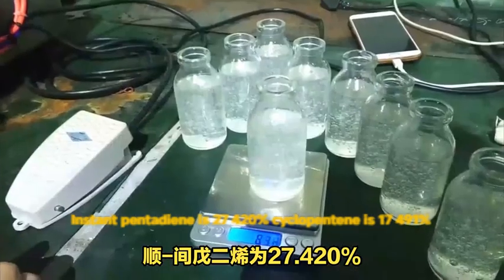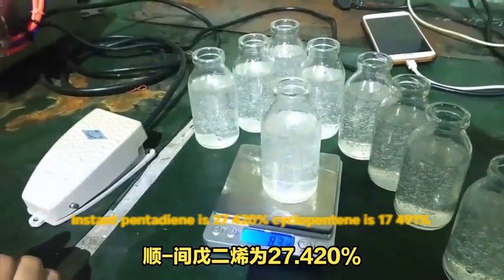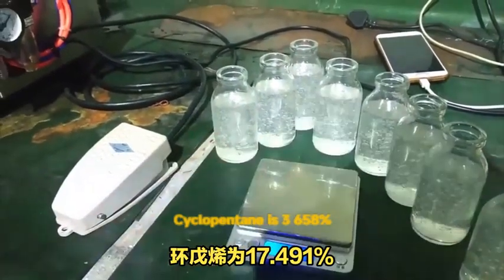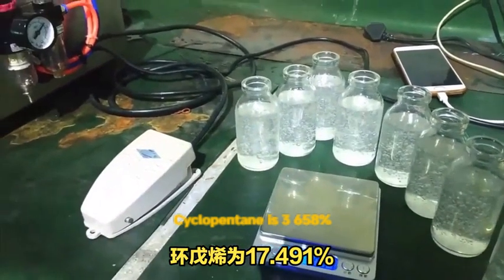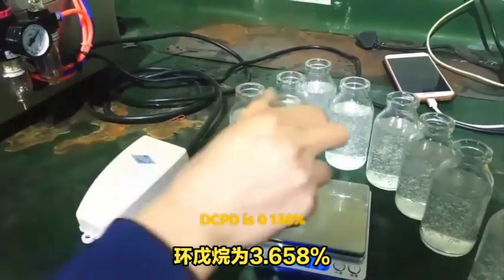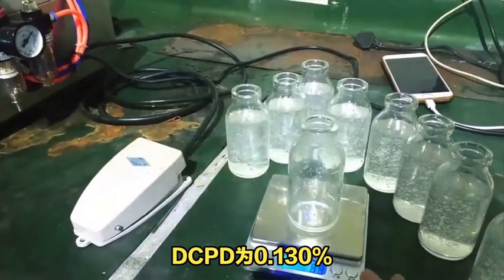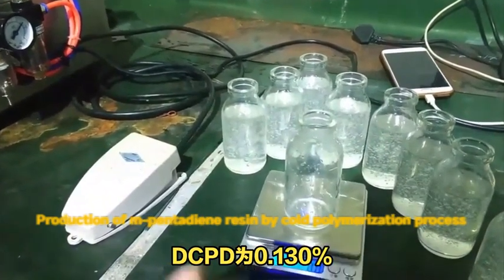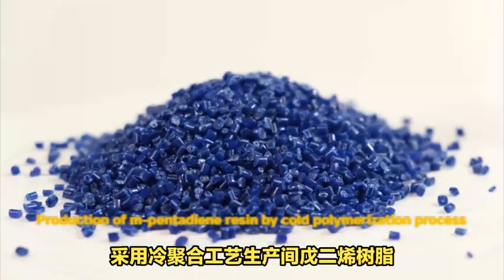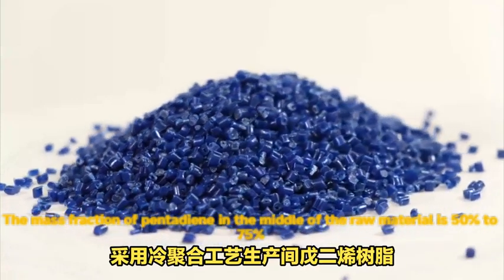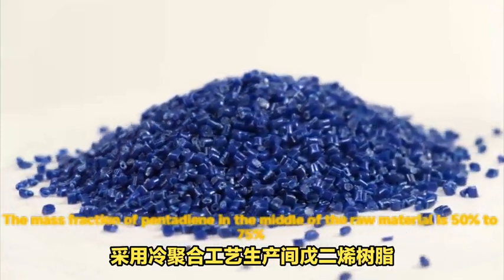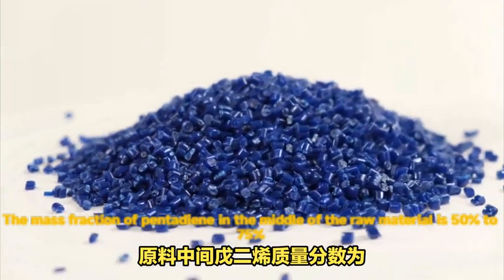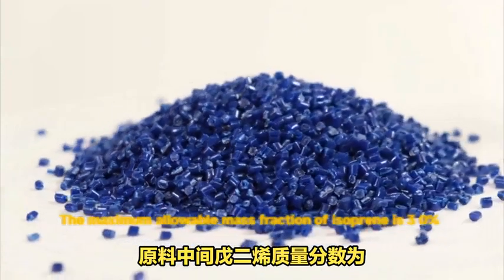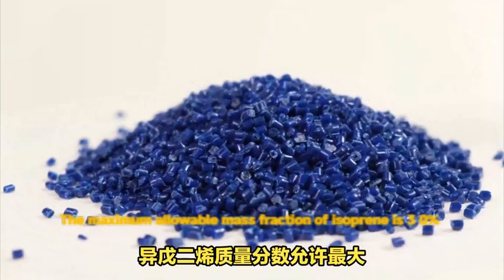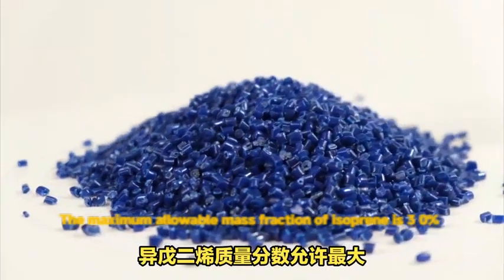Cyclopentene is 17.491%, cyclopentane is 3.658%, DCPD is 0.130%. In the production of C5 resin by the cold polymerization process, the mass fraction of piperylene in the raw material is 50% to 75%. The maximum allowable mass fraction of isoprene is 3.0%.